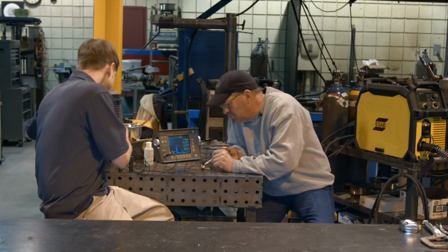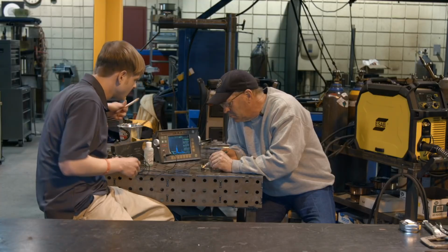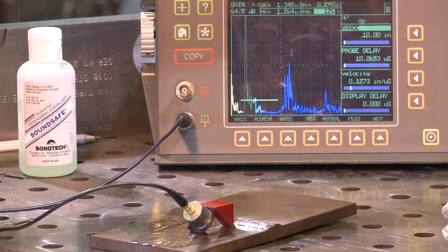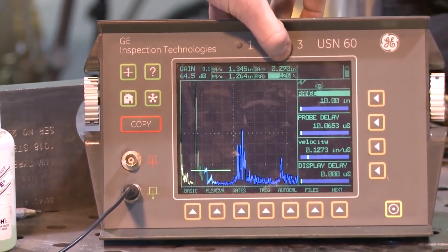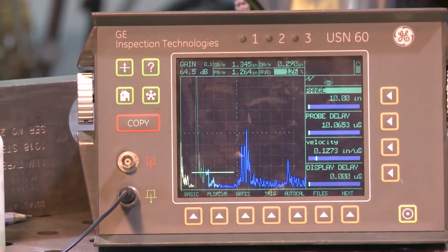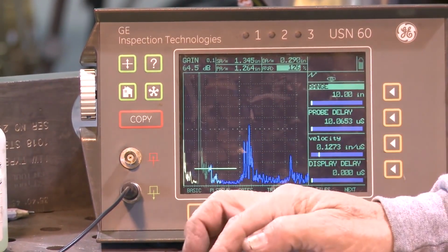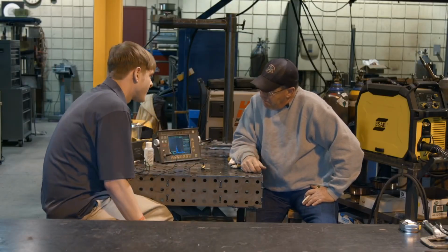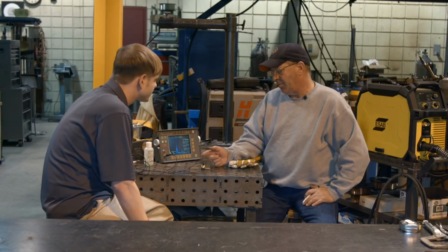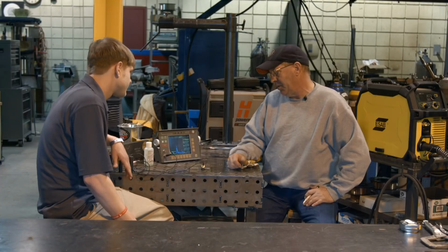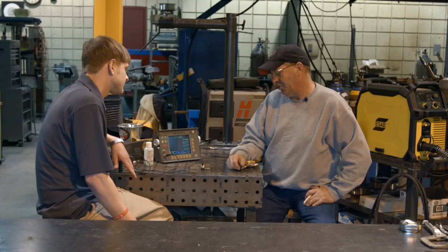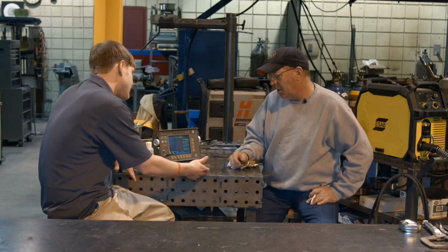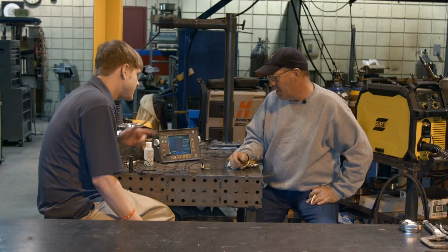And I can even tell you, ooh, that's much better, this depth reading right here is going to tell me that flaw is 0.29 inches down into the material. Now we've got a 3/8 plate here. Top down, from the top of the weld? Yes, sir, 0.29. So we're about middle of the weld actually. We're about halfway through the material in the weld nugget. It's on the lower portion because this is a 375 plate.